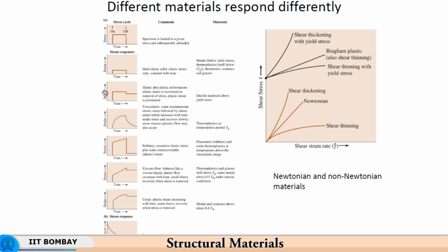There is a time lag between the two. So, viscoelastic response or viscoelastic strains differ very significantly as compared to the purely elastic solid. So, here you see that there is a drop over a period of time. Here still some plastic strain is retained, and the recovery of elastic strain is not as instantaneous as it is in these two cases. So, here the elastic recovery depends upon the strain rates, because once the load is removed, the response of the material is delayed. So, the strain rate starts falling down.